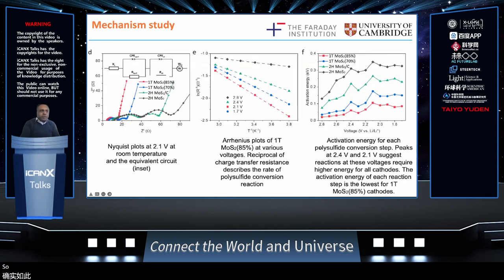So these measurements, if I go back to this slide, allow us to extract what's called the activation energy for these reactions. We have these two plateaus in the galvanostatic charge discharge characteristics, one at 2.4 and one at 2.1 volt. And we can see from the plot of the activation energy as a function of the cell voltage that there are these two peaks located at those two plateaus. So we measured the activation energy using different electrodes, and we find that the overall activation energy is quite low for the metallic phase 1T MoS2.